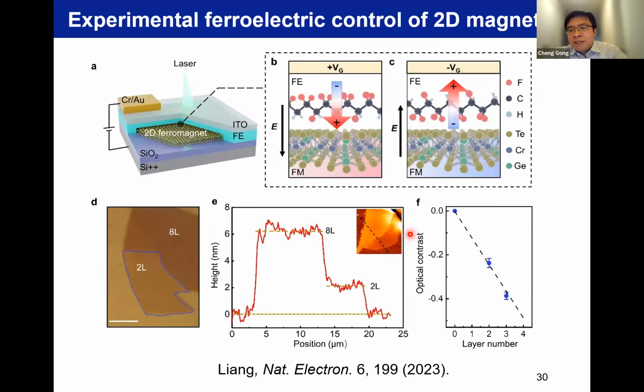And going back to what we discussed about ferroelectric control of 2D magnets, this is another piece of experimental work. You can see here a 2D CGT, chromium germanium telluride, and we deposit the polymer ferroelectric PVDF-TrFE, and then use a transparent ITO electrode, so we can apply voltage but still use optical methods to probe the magnetic properties of these 2D magnetic materials. So as you can see, this is what I mentioned.